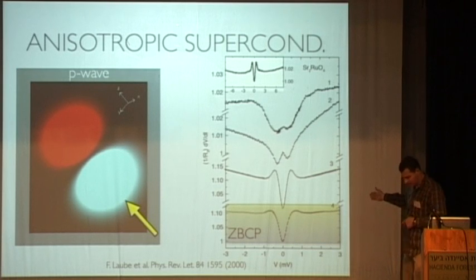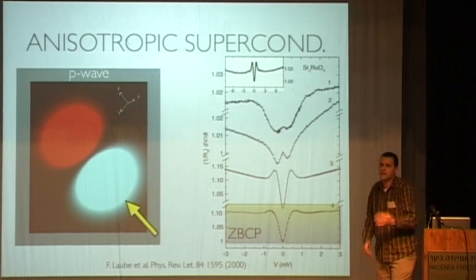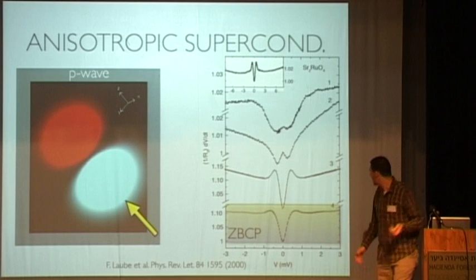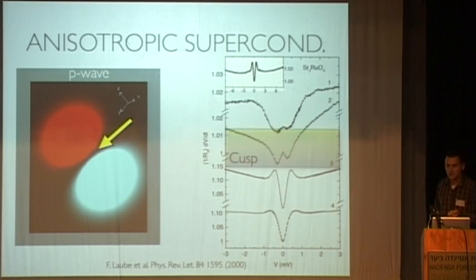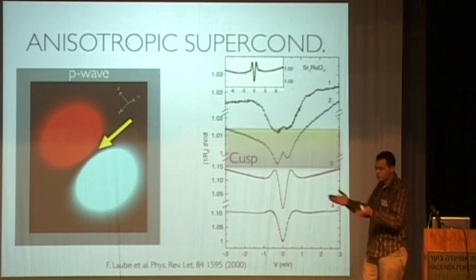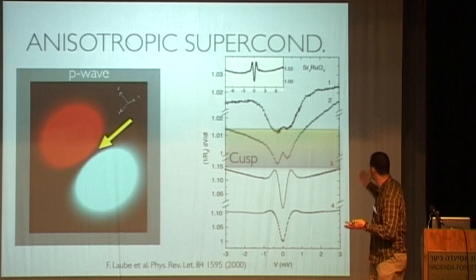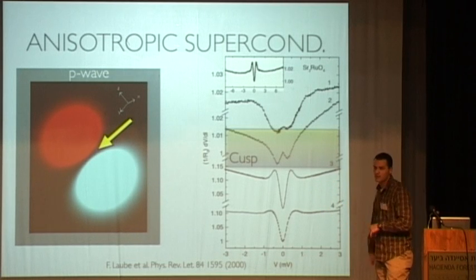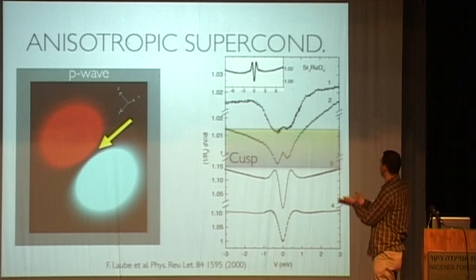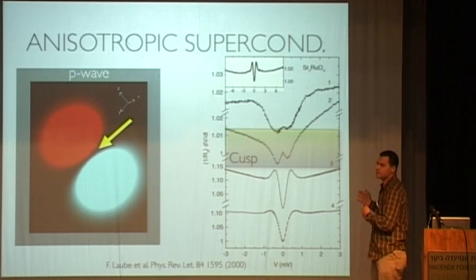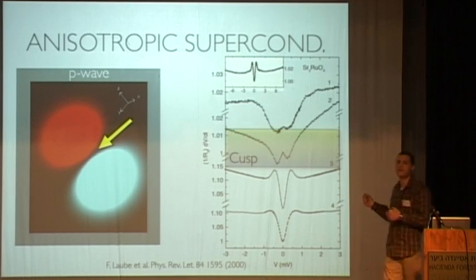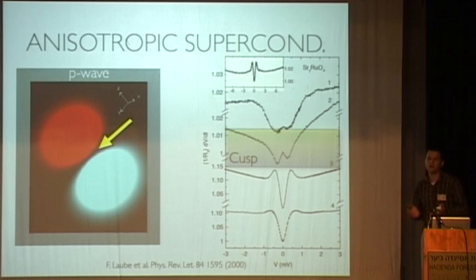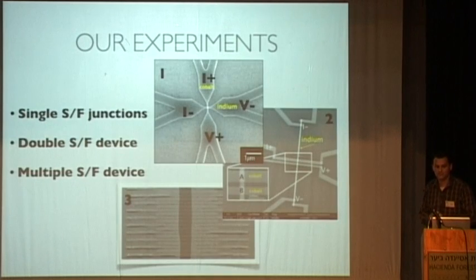This is resistance, but you see enhancement in the conductance, never mind why. And if you come from a different direction, you see what we call a V-shaped cusp. This is a resistance, so 1 over the resistance is the conductance. You see a V-shape. And this can be used as a tool to identify the symmetry of the order parameter and the kind of pairing in the superconductor.